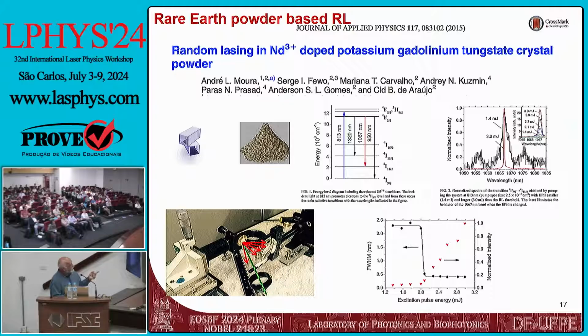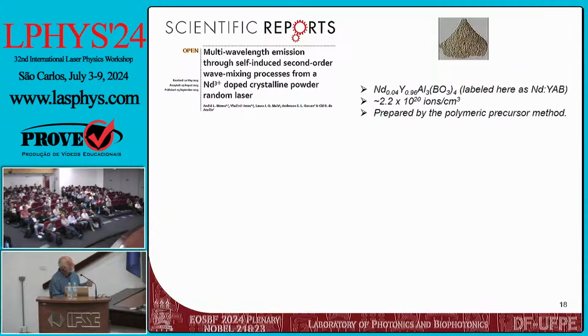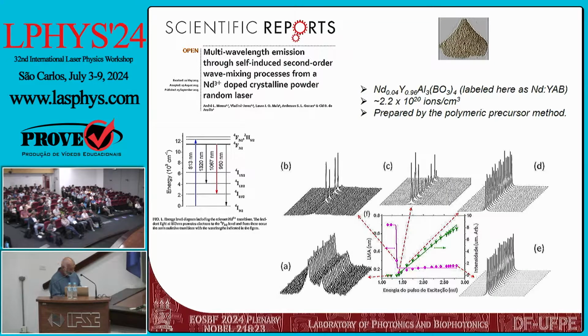So this is one example, but you can go from the bottom up. You can prepare nanoparticles through some chemical process. And again, you can have random laser emission. In this case, I'm showing 5 different excitation energies. Here you have several spectra, about 20 or so, and it's below threshold in this region here. As you go around threshold, you see the fluctuation is very high, and then above threshold it fluctuates more than below, but less than around threshold, and it's very thin, so this is in the lasing regime. So we're going to exploit and analyze carefully this intensity fluctuation, and that is going to give us a lot of information.